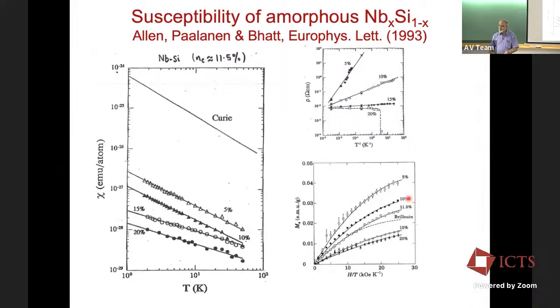But if you look at the data overall, what you find is it's very similar. All three of them behave similarly, and all three have issues of stability: you must make your measurements at cold temperatures, and once you've heated it to room temperature, you can forget about the sample. So those are problems that still plague this system. This data only goes up to 30 Kelvin because all the data was taken at low temperature, and then we said we're going to throw away the sample after these measurements, so let's heat it and get the data at as high a temperature as we feel the composition is not changing. That's where the data ends.